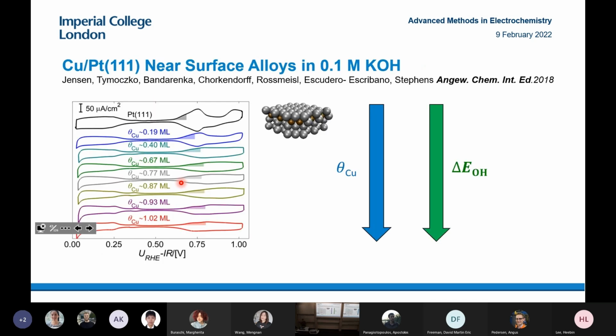So anyway, we went ahead. This was from a student in Denmark, Kim Jensen. He put different amounts of copper on a platinum single crystal and measured the OH binding. And just the same as in acid, we found that the more copper you put on the surface, the more destabilization of OH you get.